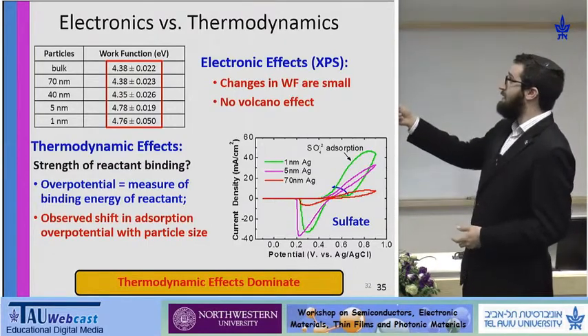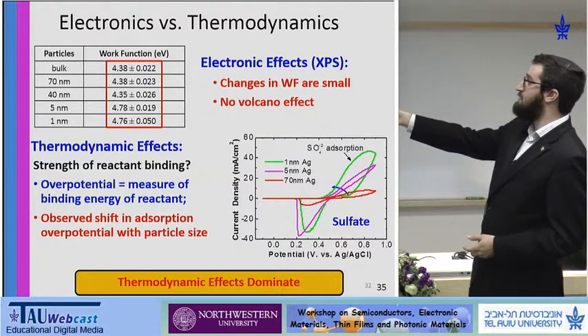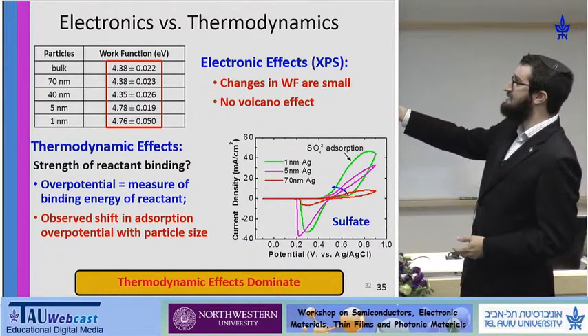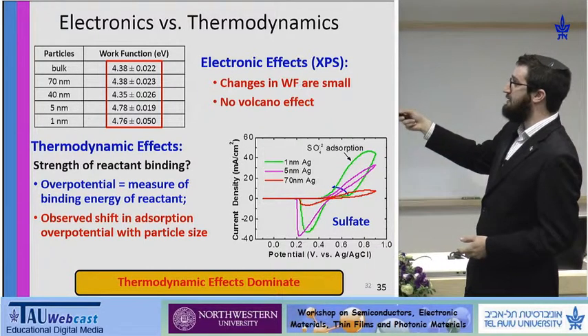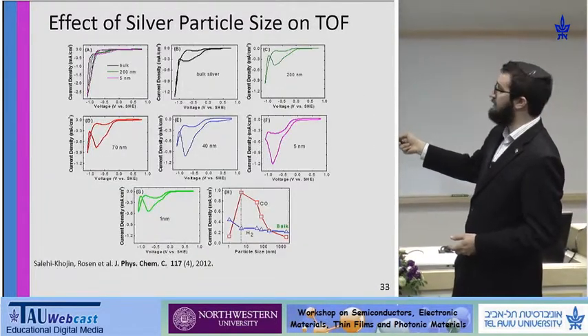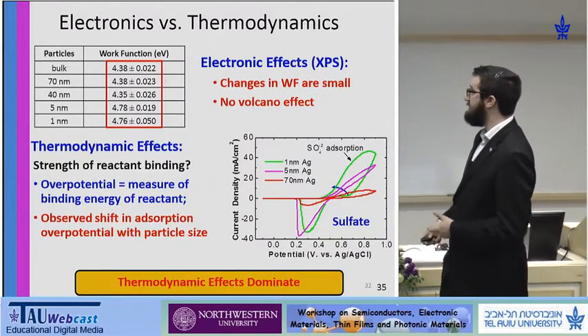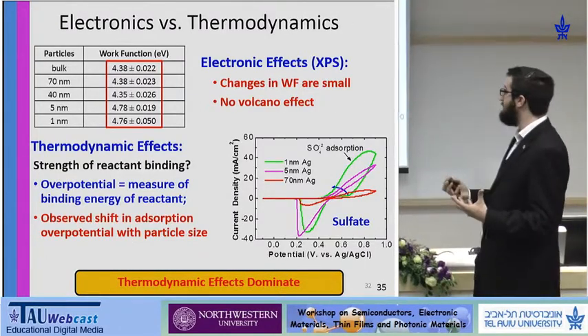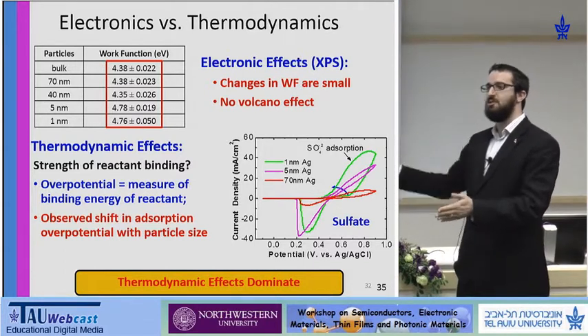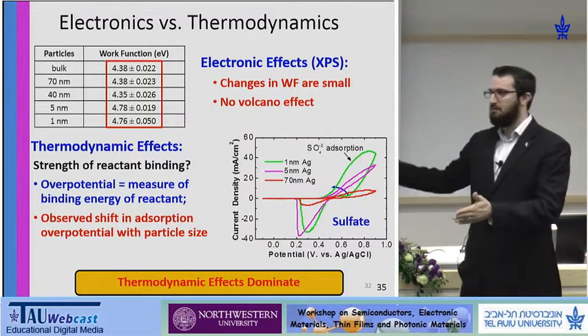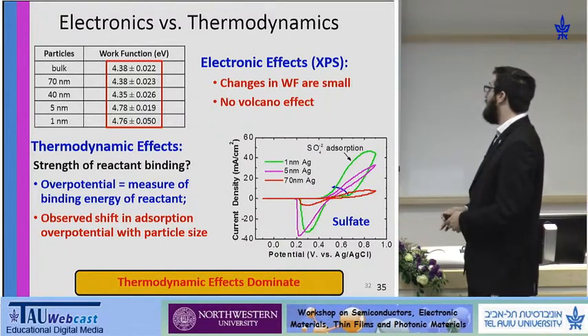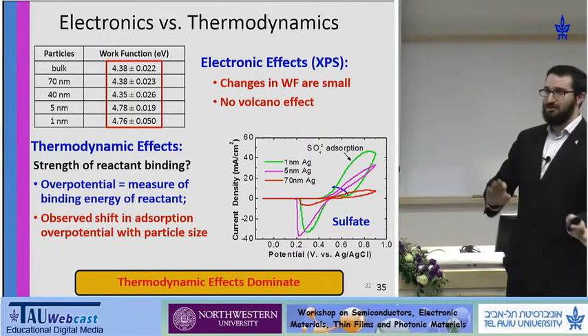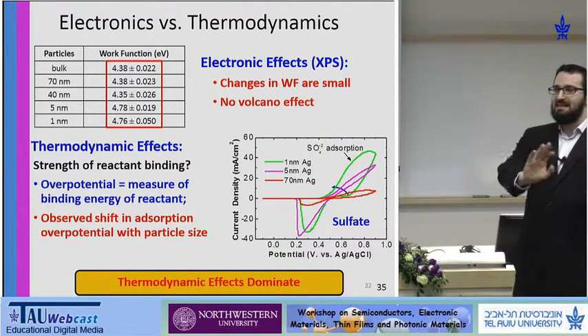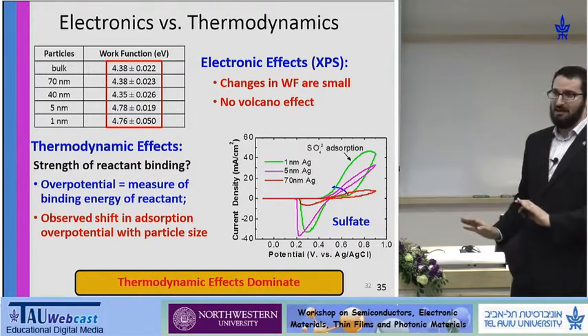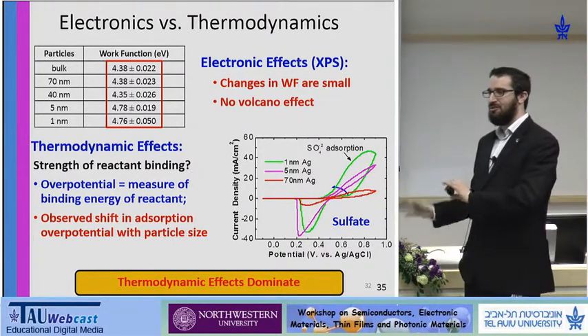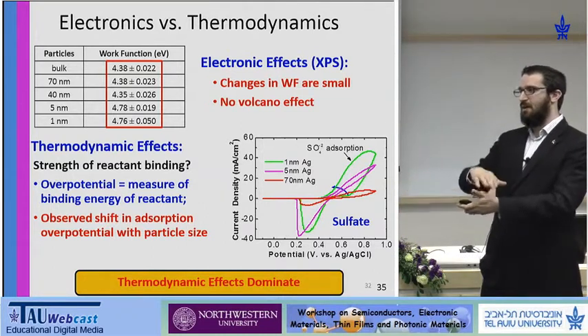We looked at electronic properties by comparing the work function of bulk to 1 nanometer particles, and we see that there's not a significant difference in the work function, at least not enough to explain the large difference in catalytic activity. But what we did see is, if we are doing an electrochemical experiment where we're trying to either adsorb and desorb a species, either sulfate, hydroxide, carbon monoxide, your species of choice, there is a significant difference in the overpotential required to facilitate the adsorption and the desorption based on the particle size. And this has to do with the energy required to facilitate the adsorption based on the size of the particle.